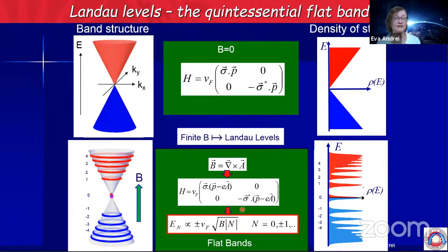So if you solve this, you see that the Landau level energy goes like the square root of the applied magnetic field multiplied by the Landau level index, which runs over these integers. You see the prefactor here is the Fermi velocity. So if you're able to measure this Landau level spectrum, you can immediately extract the Fermi velocity of these electrons in graphene.